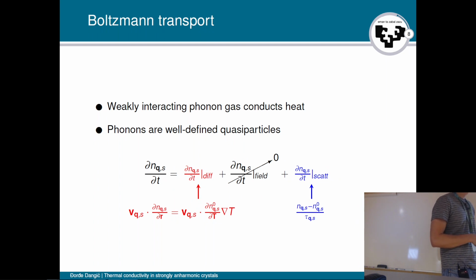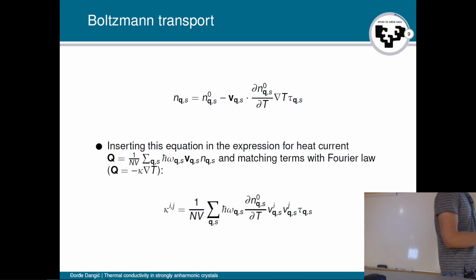Okay, and then in the steady state, we know that the change of the population of phonons with time should be 0. Then we equate everything to 0, and we get the expression for the population of the phonons. So what we do next is just insert this expression into the heat current definition. The heat current here is defined as this expression. We will not derive this part, but this is the definition of the heat current. As you can see here, we need phonon frequencies, phonon group velocities, and the phonon populations. So instead of phonon populations, we write this one, and we disregard the constant term.